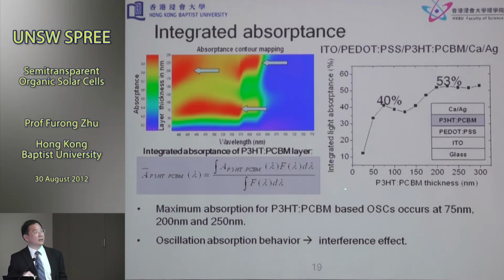We want to scan the thicknesses and see theoretically how much light is being captured by cells like this. Experimentally it's very tedious, because you need to control the time and do very many thicknesses. It's quite complicated and very difficult to do. So theoretically, using the optical admittance method that I mentioned earlier, because you're only interested in the absorbance in this region, the blend region, you can calculate the integrated absorbance as a function of its thickness.